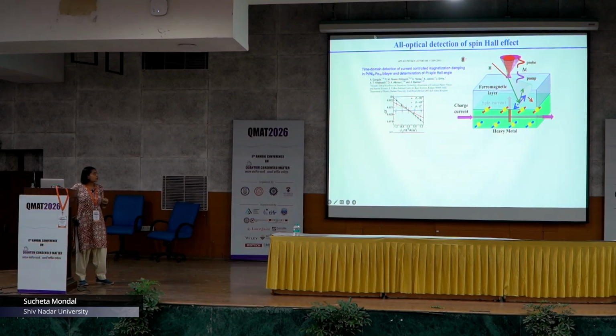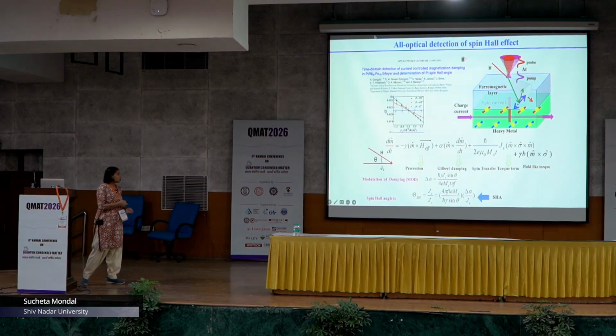The probe pulse will now detect the dynamics and will help me passively detect the efficiency of the heavy metal layer. This is the modified Landau-Lifshitz-Gilbert equation, where the first term corresponds to precession, the second term is damping, the third term is the spin transfer torque term, and the last term is field-like torque. So by calculating a little bit this spin transfer torque term, modulation of damping can be represented with these parameters and experimentally can be found.